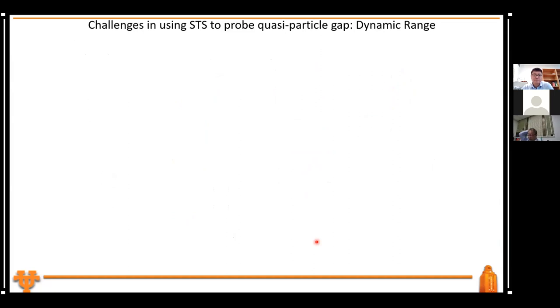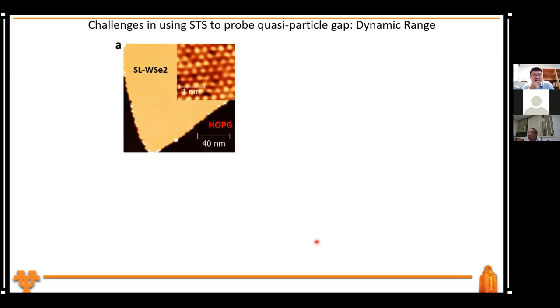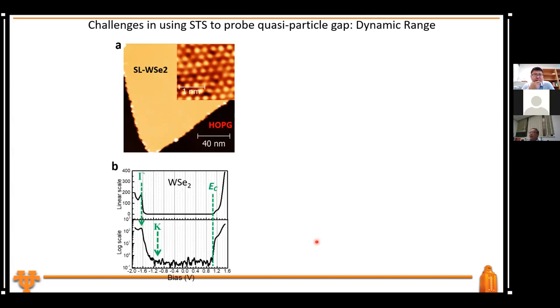So we came up with a scheme to probe the quasi-particle band gap. The challenge in using scanning tunneling spectroscopy is the dynamic range. I'm going to use this example. Say you have a single layer of WSe2. The effect is quite dramatic, right? If I take a typical tunneling spectroscopy, this is a dI/dV in the linear scale, then you would usually assign from here to here as the band gap.